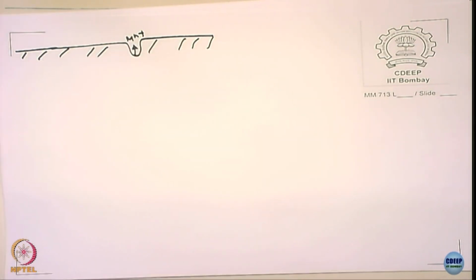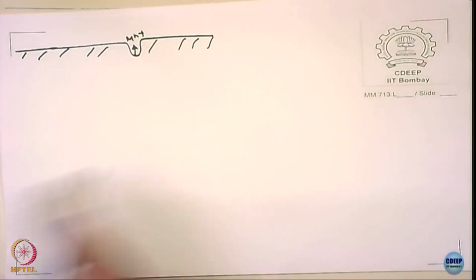So what will happen? Increase or decrease? Decrease. Why will it decrease? No, you are right, pitting will not occur. Why is it not happening? What do the metal ions first of all do? If they stay here, they hydrolyze and form hydrogen ions. If these ions are quickly moving away from the surface, what will happen to acid formation? The acid formation reduces, the chloride ion migration also reduces, and so the pit becomes unstable, okay.